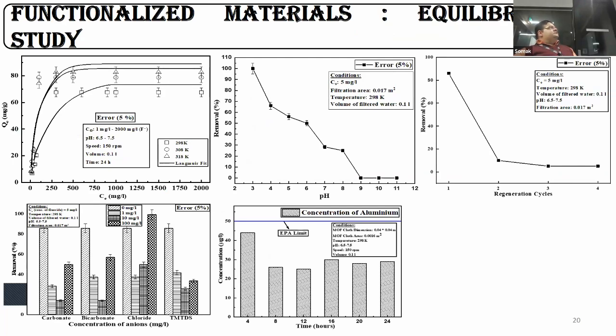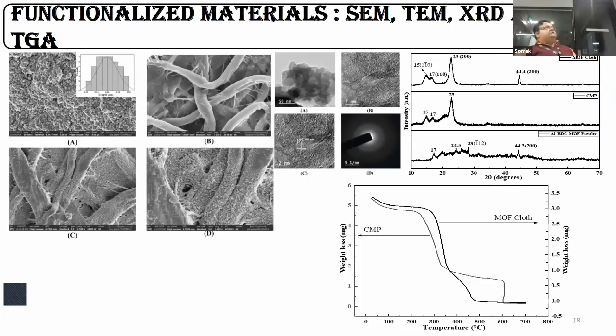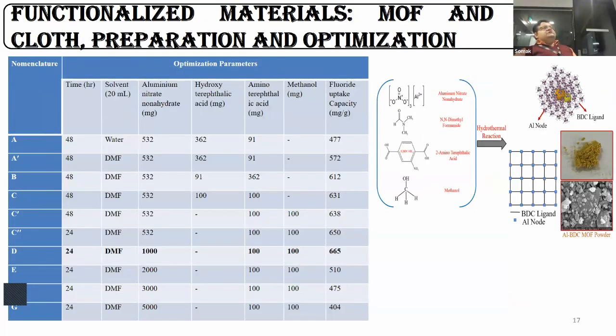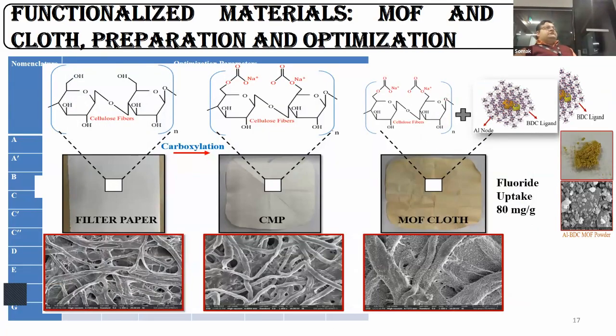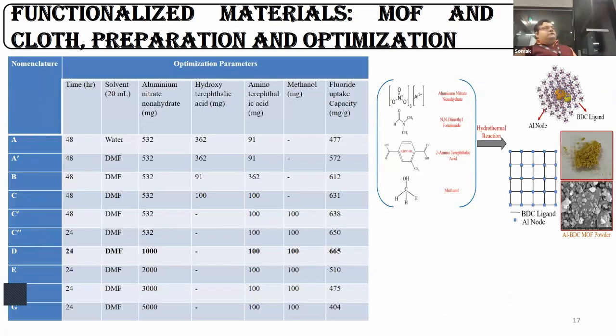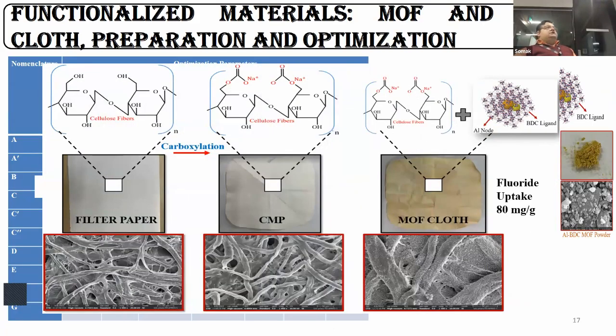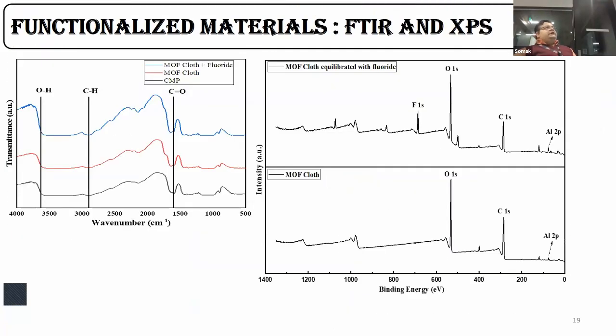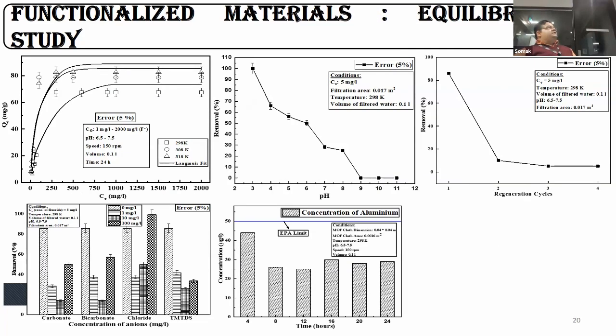Again, we carried out different equilibrium studies. So I'll go back to the previous slides to show that in this case it was around 665, but as the yield is very low, we have to immobilize it in a material to get something usable for daily application. So from 665, as it gets immobilized and some MOF is lost, the defluoridation capacity decreases to 80 milligrams per gram, but it's still high. We carried out an analysis for the equilibrium study and were able to see that as the temperature keeps rising, the uptake capacity of fluoride also increases, suggesting an endothermic adsorption mechanism.